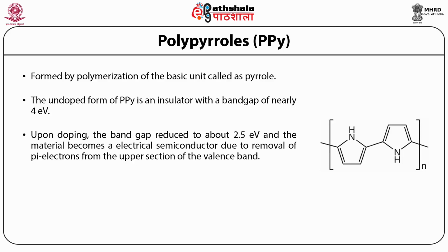One needs to dope the polymer polypyrrole to achieve a conducting polymer, which is typically achieved by the oxidation of the polymer, that is by p-type doping. In the case of p-type doping, the process can be carried out electrochemically, which helps in achieving the high purity conducting films of the polymers easily. The films deposited on the electrodes are immersed in the electrolyte. Their thickness and composition can be controlled quite easily by varying the process parameters such as voltage, current, concentration, etc.